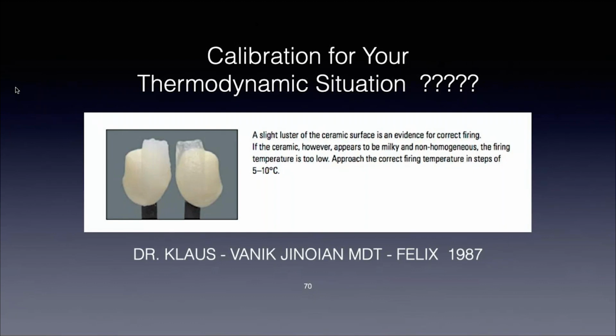And so you could achieve both, but the best way to do this is to take a coping of the material that you're going to layer, and you build it up with window porcelain or clear porcelain, whatever you have, and build it up and extend it a little bit. And then you just take the end of your brush and you chip away a little bit at the margins. And when you fire that, if that edge is still sharp and the material is clear, then you've got the temperature honed in perfectly. Just because you set the furnace on whatever temperature doesn't mean it's going to bake that way, because your thermodynamic situation changes all the time.